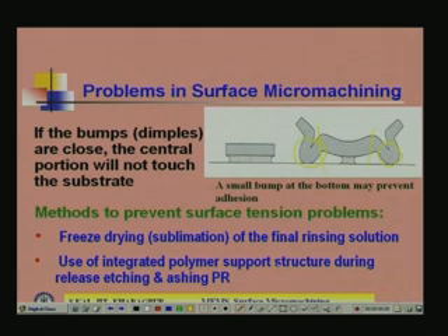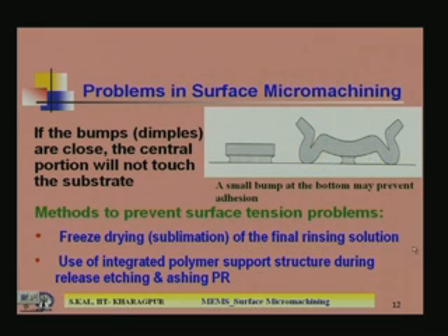Use of integrated polymer support structure during release etching and ashing of PR. Some support structure; ashing of PR means photoresist ashing, which is used in dry processing, plasma processing, where the photoresist is burned and removed. Or you can use some small polymer support structures like this one mentioned here, in order to prevent breaking of the structures. So, these are some of the solutions for surface micromachining.